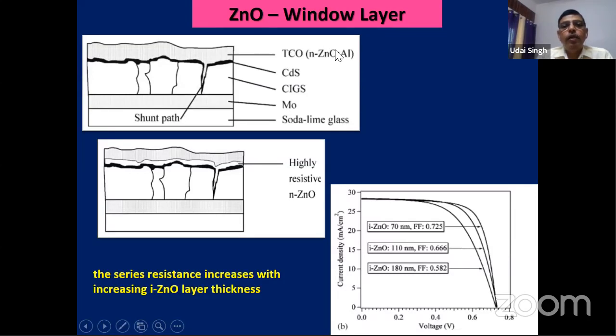After that, before the transparent conducting oxide, people have tried to use one layer of highly resistive intrinsic layer. What happens if you don't use this highly resistive intrinsic layer? Because when you are depositing, there may be chances you have some pinholes, some defects. So when you deposit the contact, there may be some shunting path. It may not be visible when you are measuring now. Maybe after 1 week when you measure, it may have shorted.